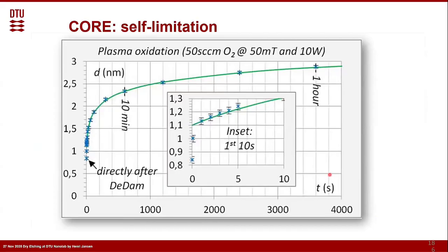Now, core has something else because core is using oxidation, but plasma oxidation is self-limiting. So if I take an oxygen plasma to make the oxide and I want to oxidize the silicon, it just stops after, let's say, maybe a few nanometers. Here you can see the time. It takes more than 1 hour to grow 3 nanometers of oxide. So it's a very thin layer. And already after a few seconds, it's already 1 nanometer. So it's a very quick logarithmic process where only in the beginning it is there, but then after that, it doesn't do that much anymore. That's what we call self-limiting.